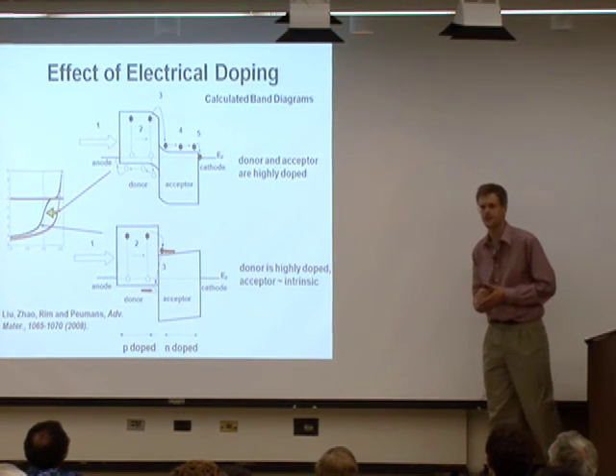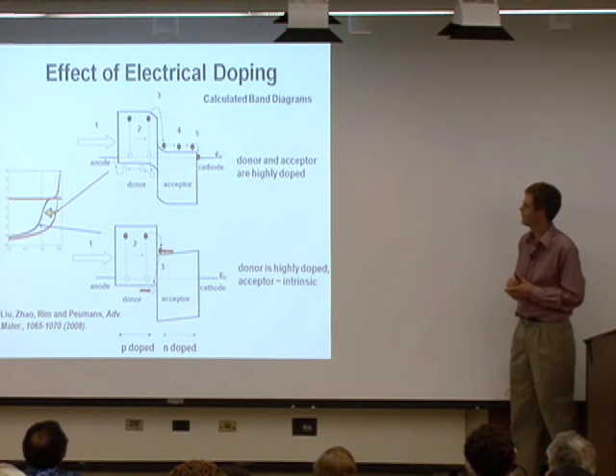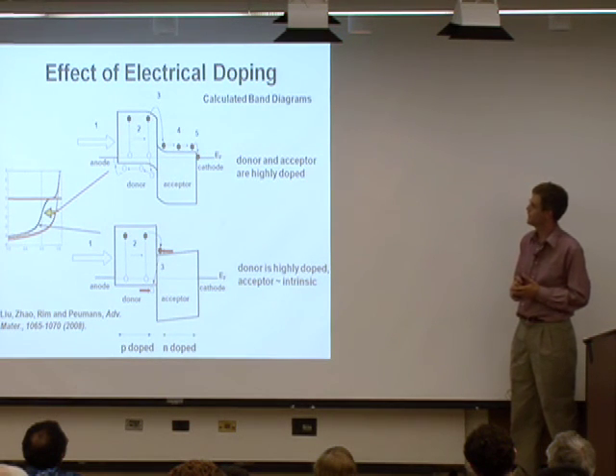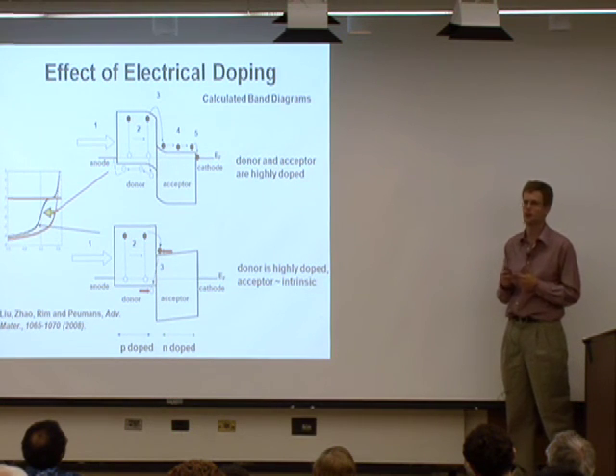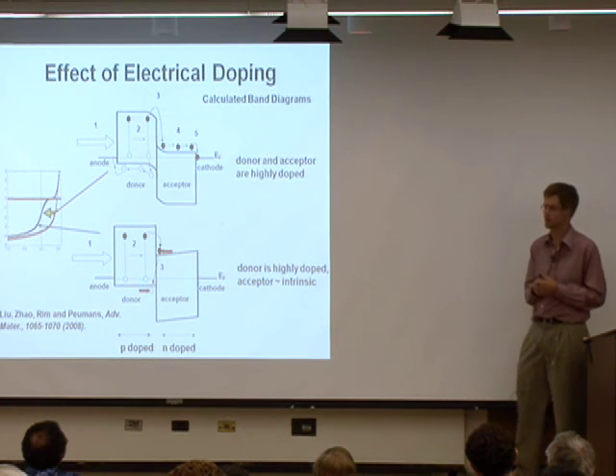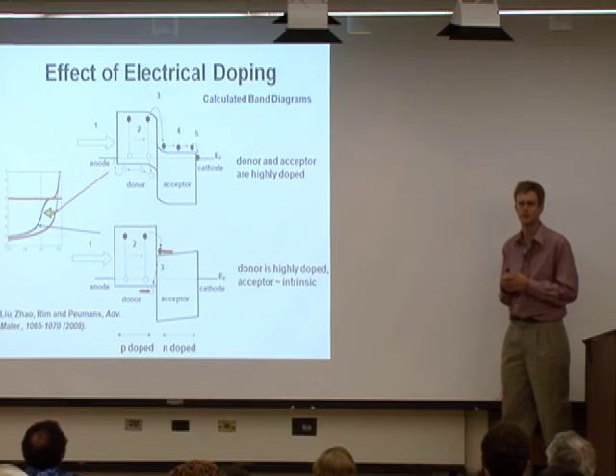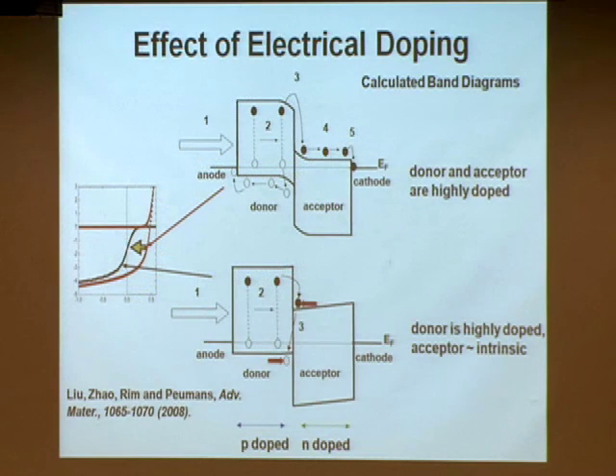I think one of the most exciting discoveries that his group has made in the last year or so is they figured out that a lot of the polymers, a lot of the molecules people were using were doped, even though they had not done that intentionally. There were undesired impurities that were doping the material. And what that ended up doing is concentrating the electric field at the interface. It created a PN junction. And then they found when they purified the materials, then they lost the doping, and now the electric field would be spread out over the entire film. That actually turns out to be bad.